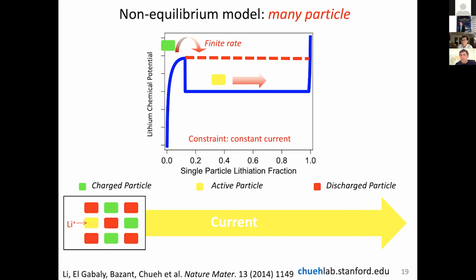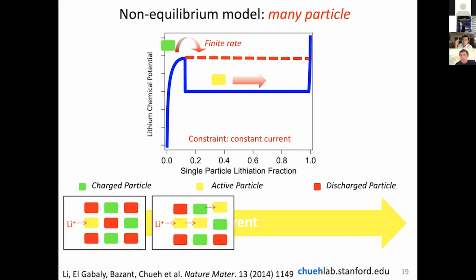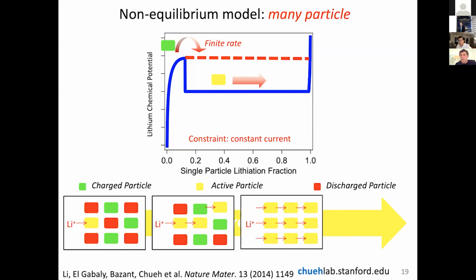But now if you want more current to come out of the battery, you would just slightly increase the position of the red line to increase the driving force, but nucleation rate is very sensitive to potential. So then you will cause more particles to nucleate at a faster rate, but each one of those particles approximately sees the same driving force. So that's why the arrow, or the speed of intercalation per particle, remains the same. So as you increase the current, you are tuning up the intercalation and the nucleation rate, but you're not tuning the growth rate. And this is what fixes the particle lithiation time, because you're fixing the driving force for the growth of the second phase.